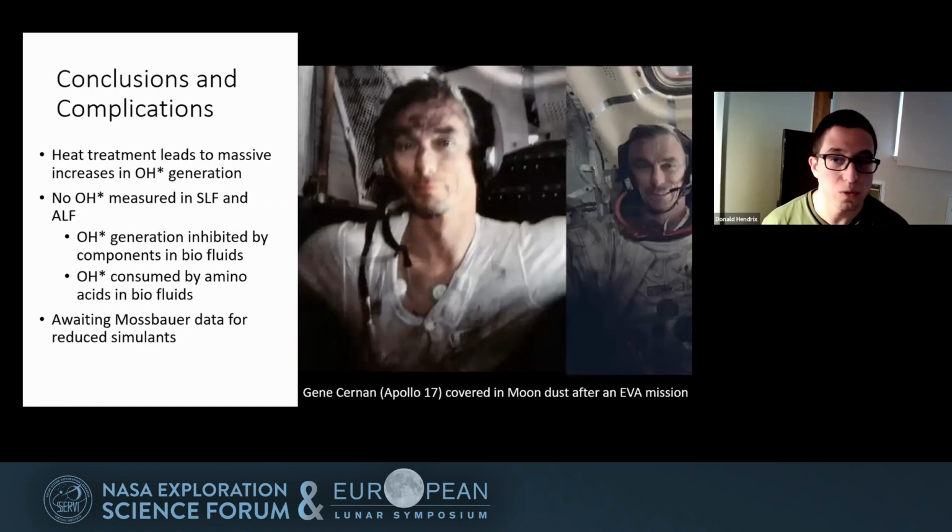And so to conclude, heat treatment and reduction leads to massive increases of OH radical in DI water, at least, and that's very likely due to the presence of metallic iron. So we were not able to measure OH radical in simulated lung fluid or artificial lysosomal fluid. However, that does not mean that we're not making OH radical. It could be that we're not, but in all honesty, it could be a mix of both.